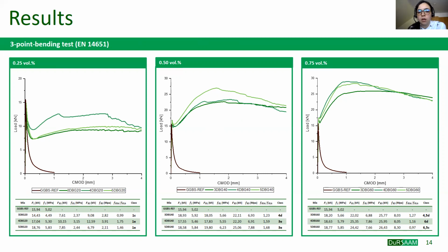at their best. With an increase of the fiber content from 0.25 to 0.50 or even to 0.75, the performances of the fibers are quite similar, even if the 3D fibers are the ones with the lowest post-cracking residual flexural strength. And 4D and 5D perform almost in the same way. And this is also due to the same explanation given before.